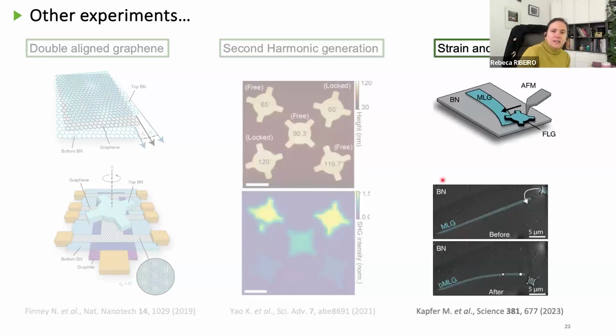And more recently, also at Columbia University, they developed a technique that uses these beautiful handles pushed with AFM to make bent systems. These bent systems allow us to control the angle locally, which means that we're going to have a gradient of angular alignment through the whole ribbon, and also to create strain. So now you can control the optical properties, mechanical properties. You can create strain at will. So it's a kind of powerful technique.